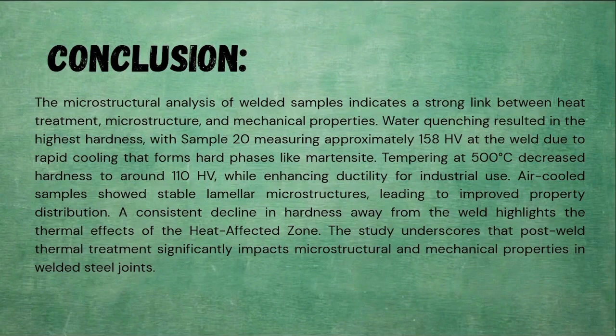Second, tempering after quenching, applied at 500 degrees Celsius for 20 minutes, reduced peak hardness to around 110 HV. While this means a loss in maximum strength, it relieves residual stresses and transforms some of the brittle martensite into more stable phases, improving toughness and ductility, making the material more practical for real-world use.